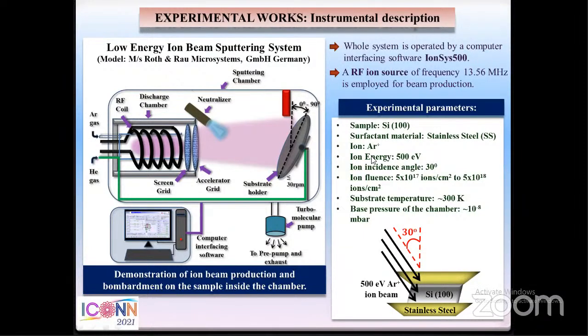Sorry for the interruption. Is it a surfactant material or substrate material? The stainless steel is the surfactant material, and the substrate is the silicon. Okay, so the ion beam that is used to bombard the sample is the argon ion beam of energy 500 eV. So the argon ion beam is used to bombard the surface, that is the silicon, as well as the co-sputtering material, at an incidence angle of 30 degree.